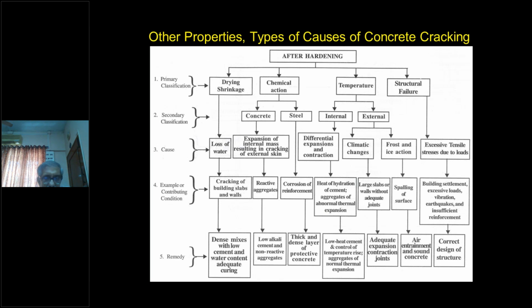So we have to use, if it's a massive pour, a low heat cement. Pozzolanic additions and slag additions are recommended, or PPC or slag cement can be used in such instances so that the extreme temperatures inside the concrete do not happen. The next we go is the external ambient temperature. Climatic changes happen and large slabs or walls without adequate joints start cracking at places where the engineer has forgotten to put joints. Now this is very, very important as far as the roads and pavements are concerned.